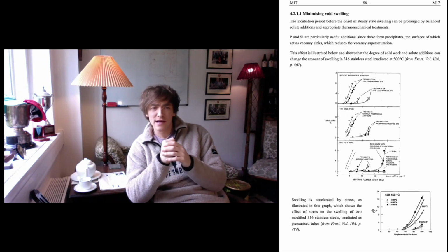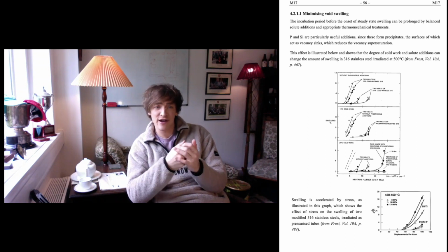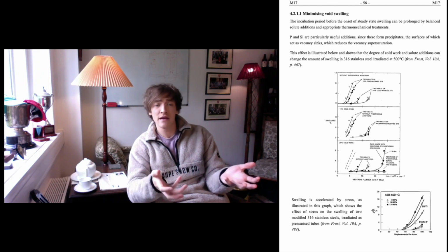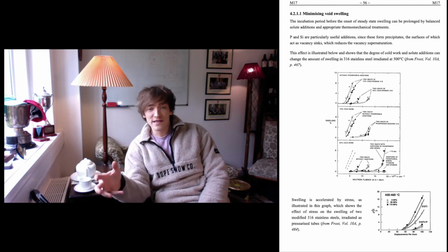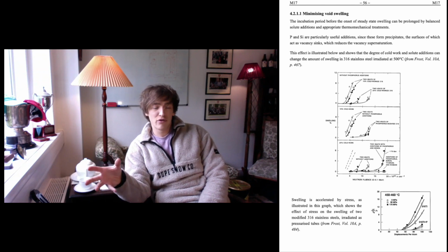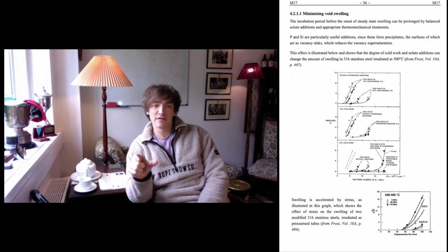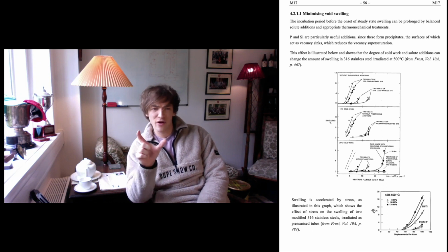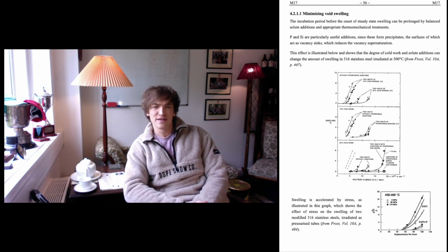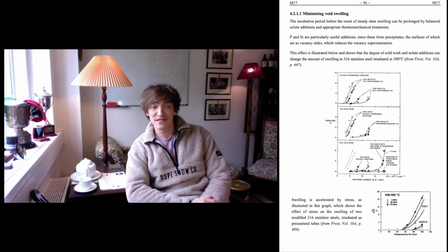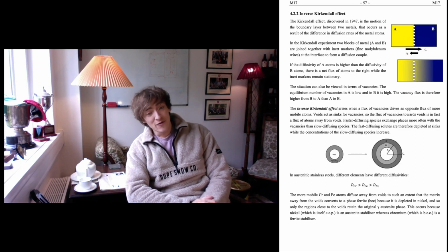Cold work can also have benefits because that creates dislocations, which again will act as sinks for vacancies, all of which inhibits swelling by prolonging that incubation period prior to the initiation of swelling. That's what you're trying to do. You need to prolong that incubation period to stop that swelling occurring. Okay? So that's what a swelling resistant alloy looks like.